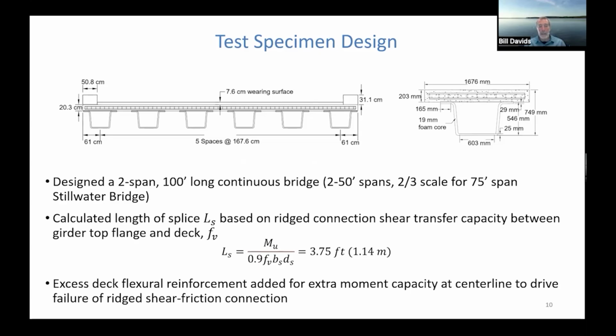And we calculated that length of splice based on what we know we can transfer across that ridged interface, based on our prior work, where we look at that when we're attaching the deck to the girder. And it's a first principles equation where the moment is simply divided by the stress transferred across that interface and the internal lever arm for bending. And it's a little bit more complicated than this. It's an iterative design process because as we infill different lengths of girder, the moments change because you change the flexural rigidity of the continuous structure. But that's okay. We can work through that.